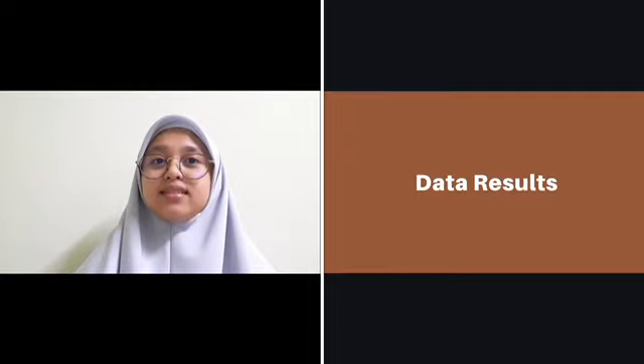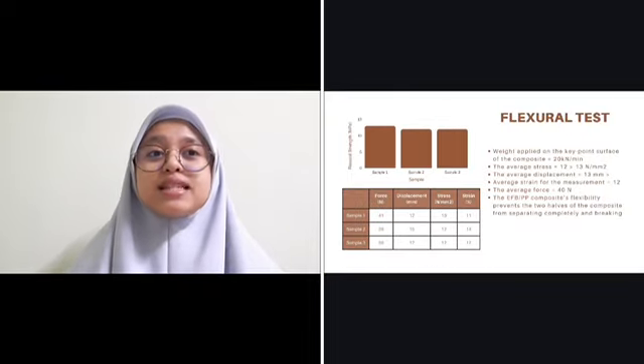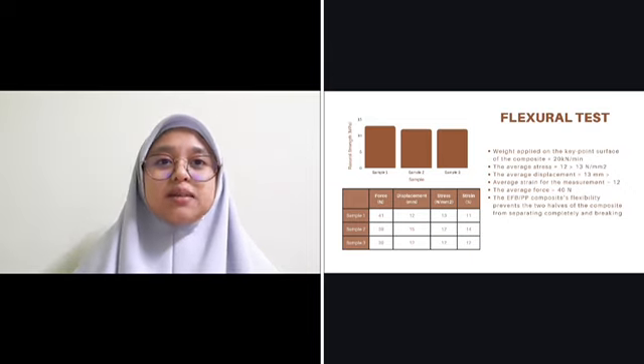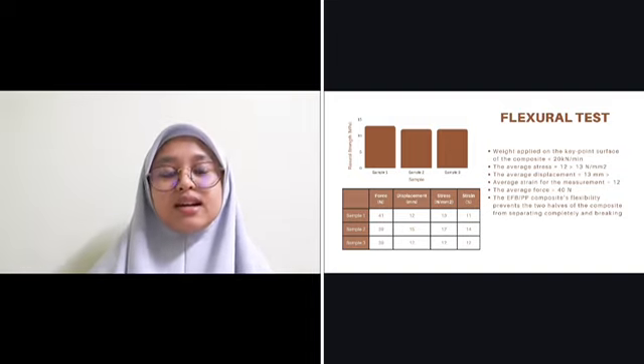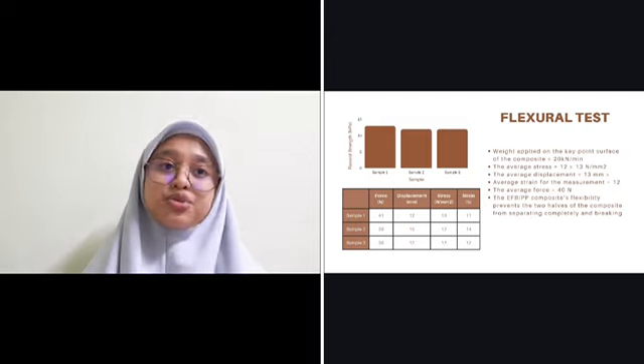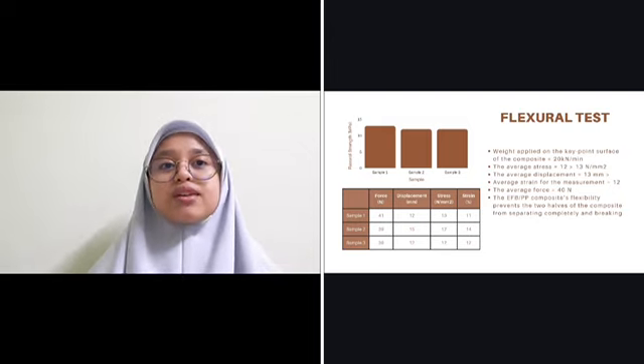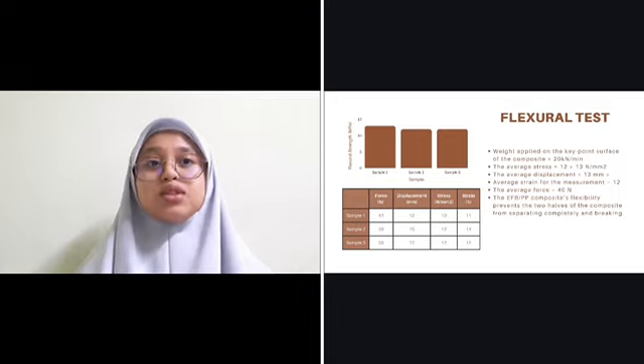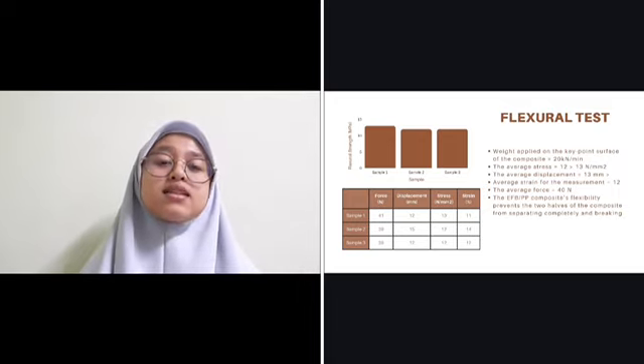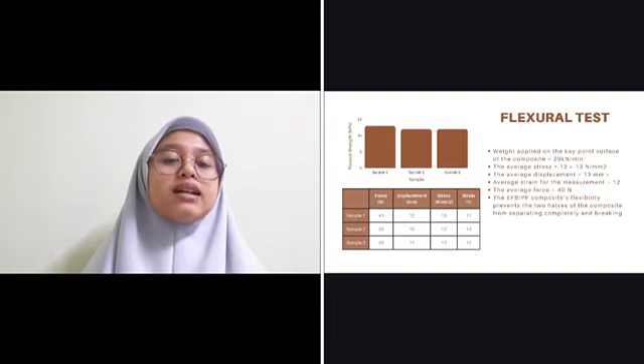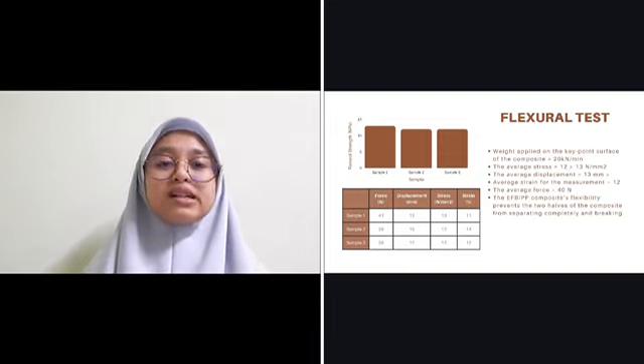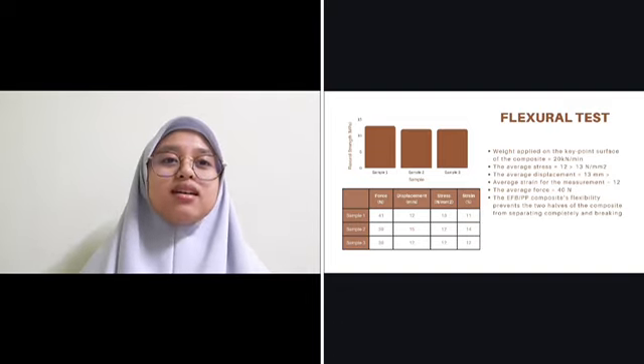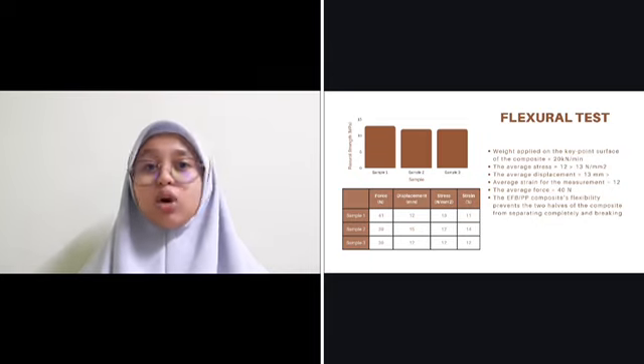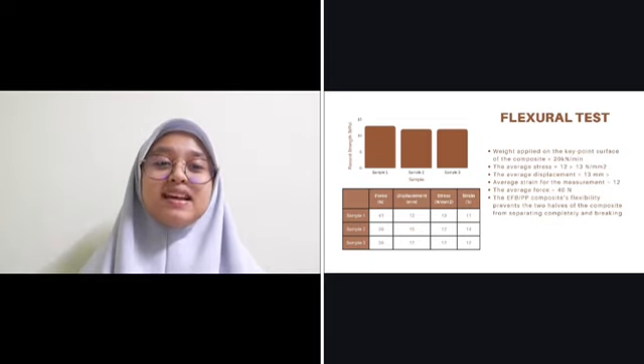Moving on to data result. The first test that was done upon the composite was the flexural strength test. The weight applied on the key point surface of the composite during the flexural test was 20 kN per minute. The average stress considered the flexural strength was 12 Newton per millimeter square, which can be as high as 13 Newton per millimeter square. The average displacement taken was 13 mm but can be higher than the value as the composite were not broken. The average strain for the measurement was 12, while the average force was 40 Newton. The composite's flexibility prevents the two halves of the composite from separating completely and breaking.